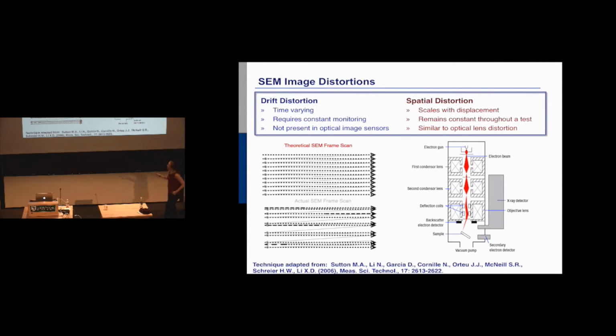So there are two different distortions that we had to work with. One was the spatial distortion, which is just due to the fact that you have these lenses. They're not perfect. They're bending the electrons. If you guys are ever on an SEM, you can see it. Pull your SEM all the way out to a big field of view, and you'll see your specimen start to warp. You can visually see it. It's because you're trying to bend the electrons so far that they start to warp the specimen image. So the spatial distortion will kill you at big fields of view. Anything above 300 microns or more, you can really start to see some warping. Pull it out to a millimeter, you'll totally see it.